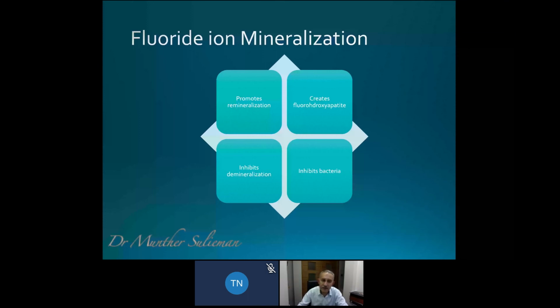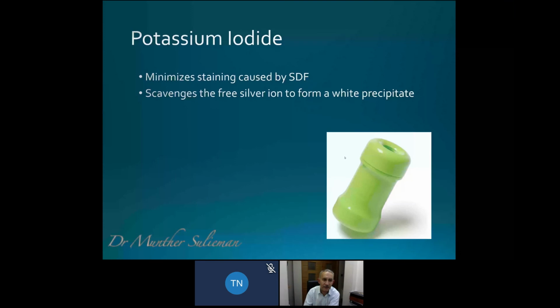Now, the use of silver is not new. The problem was it used to stain cavities, but the addition of potassium iodide scavenges the free silver ions. It produces a white precipitate, and then you basically continue to do this until you have a clear area where you see nothing there. You don't have any free silver around. That's when you know you've done the procedure.